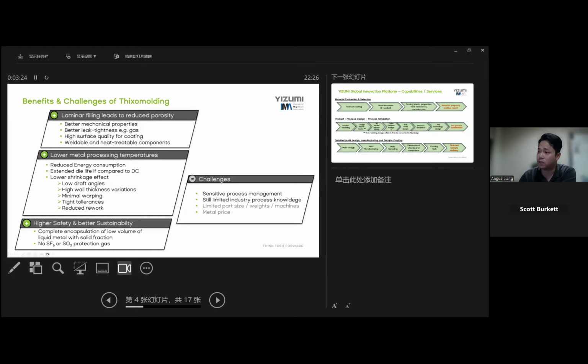We actually have a case story where a customer compared Thixomolding with hot chamber die casting, and overall we have roughly 50% energy saving compared to a hot chamber. And we definitely have extended die life compared to die casting because of this lower temperature and no injection speed, and lower shrinkage, which allows low draft angles, high wall thickness variations, minimal warping, and tighter tolerances, and reduces rework because of such precise dimensions.